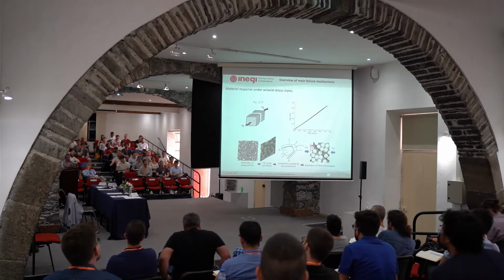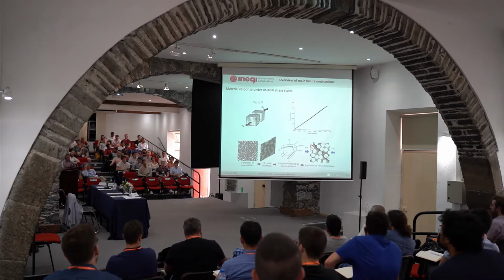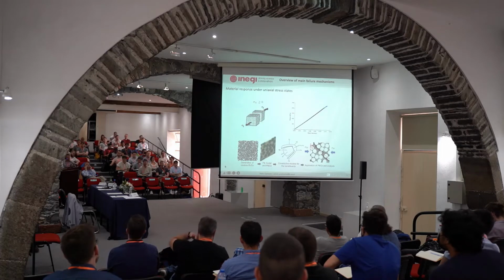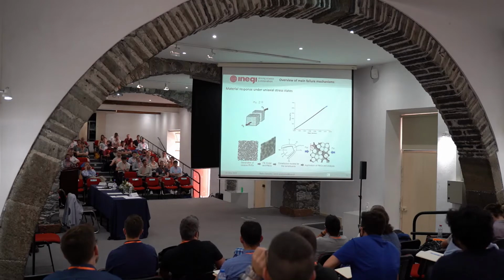So what we think we should do is to rely on computational micromechanics to see more detail in a more controlled way all these mechanisms. Our approach is based on four main building blocks. One, we generate the representative volume elements, with a random distribution of fibers, because the distribution is random. It's not periodic. Then automatically we generate a finite element model. We apply appropriate periodic boundary conditions. We have our own material models for the constituents: for the fiber, for the resin, for the fiber-matrix interface. Then we apply the boundary conditions and we run the analysis.